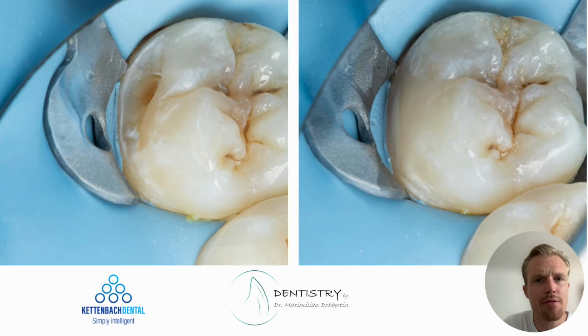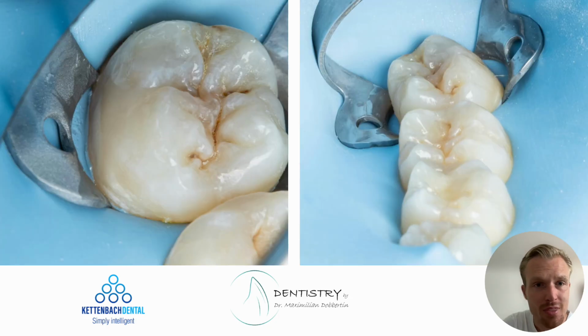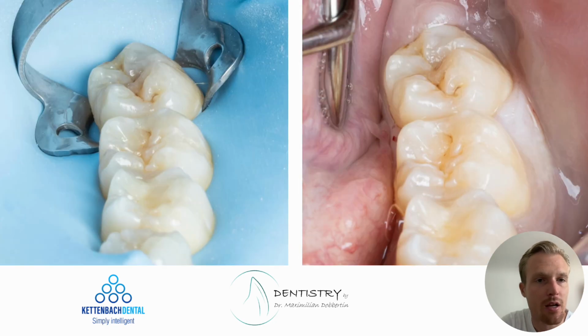And as you can see here, there's a little bit of discoloration from the inside of the tooth, which is totally fine. And the combination of both the discoloration, the color of the tooth itself, combined with the translucent and somehow light effects of the bulk fill composites can then lead to a natural looking result, as you can see here. And even after taking out the rubber dam, this is quite an aesthetic result for only using one shade in quite a limited way, other than having more shades in an incremental technique using conventional composites.